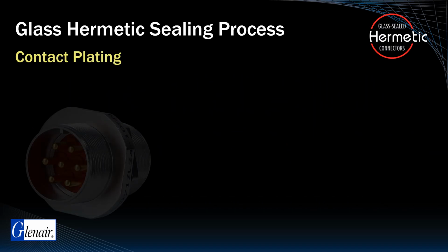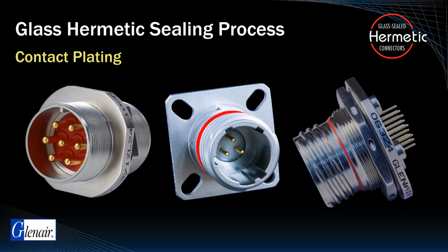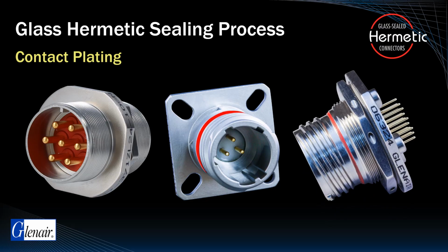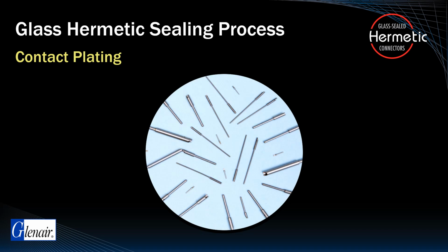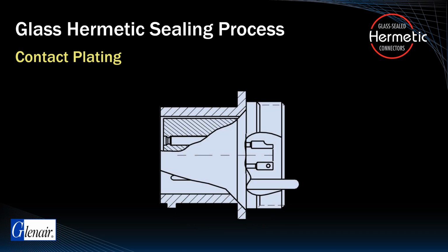At this point, plating is applied to the connector contacts. Without the benefit of surface plating, contacts would not be conductive enough to reliably transmit data or power. For that reason, the contacts, and the contacts alone in a hermetic assembly, must be plated with a conductive material, typically gold. Glass-sealed connector contacts are typically made from Kovar or specialty nickel-iron materials like Alloy 42 or Alloy 52. In this process, each contact is individually wired twice, once on the mating interface side and again on the wire termination side, and the assembly is immersed into the plating solution.